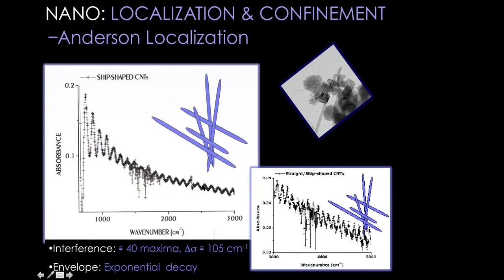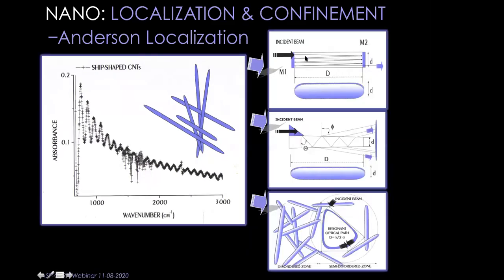And these interference fringes can be caused only by three phenomena. Either the carbon nanotubes behave individually like a resonator, which means if you take a carbon nanotube, it behaves like a resonator. So the infrared light that we send as a probe will go inside the tube and be reflected by its end, tuck, tuck, tuck, some multiple resonances, and you would have something like this. Or,